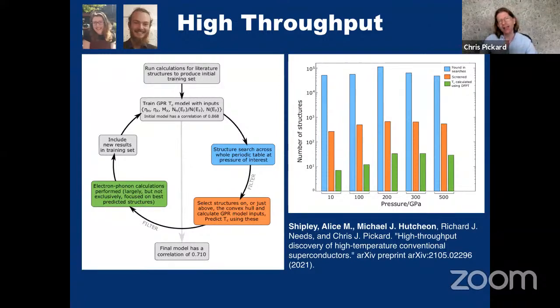Now, when I say all of them, it's not all of them, but we decided to be pragmatic and we restricted ourselves to small unit cells and we enforced high symmetry. The reason we enforced high symmetry obviously speeded the computations up, but it was also based on the observation that the good superconducting hydrides that we've seen so far, I mean, you saw the pictures, were all fairly high symmetry, fairly small unit cell structures.